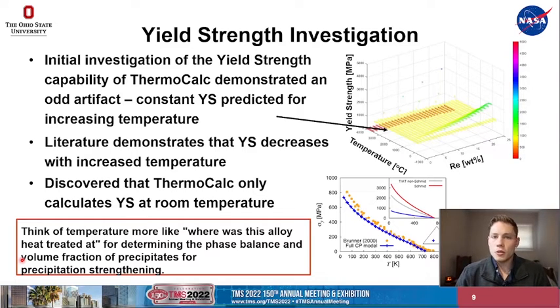And because we were not seeing these results, we had to do a deeper investigation into how the thermodynamic software that we were using was calculating or was using the inputs that we were giving. So what we found out was that it treated the temperature that we were providing as a heat treatment temperature, essentially, and always providing the yield strength at room temperature. This is a limit of the software and the data that the software uses in order to provide calculations, and it's not something that could be easily overcome. And this meant that we were not going to be able to use yield strength in order to calculate the ductile brittle transition temperature as we hoped.